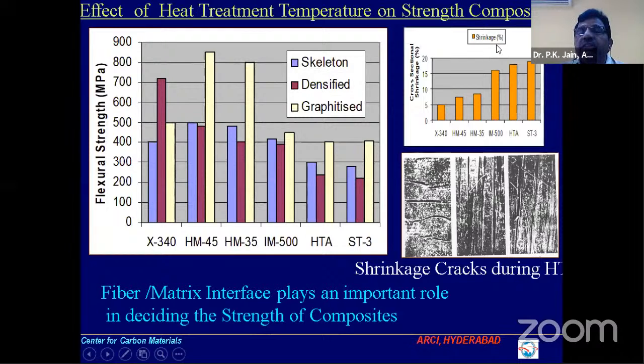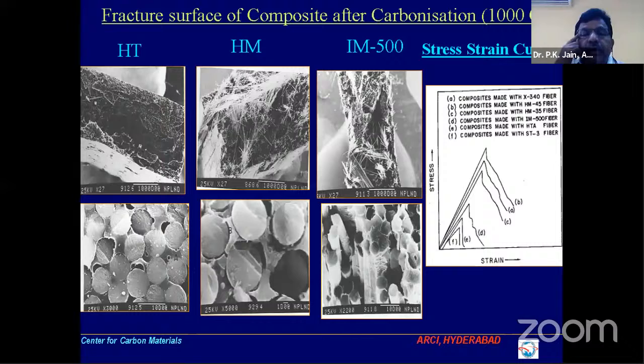And if you see the shrinkage and other properties also, the higher surface groups will lead to a higher shrinkage. It can also be observed indirectly in the micrograph. When you take the fracture of all these materials, the high strength material which has a strong fiber-matrix interface leads to a catastrophic failure.